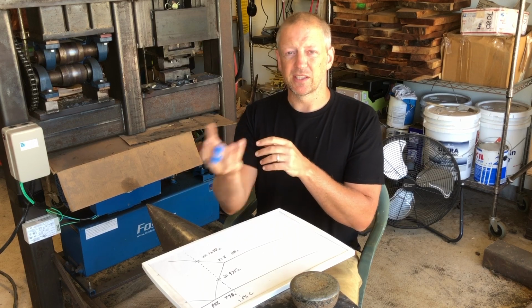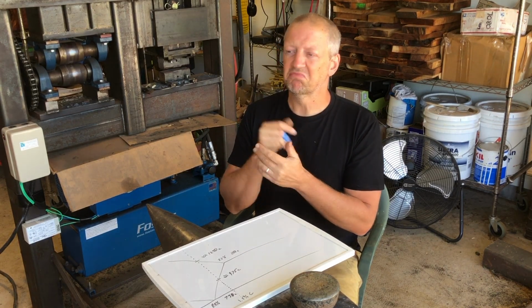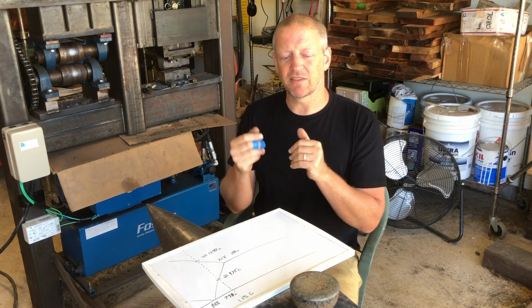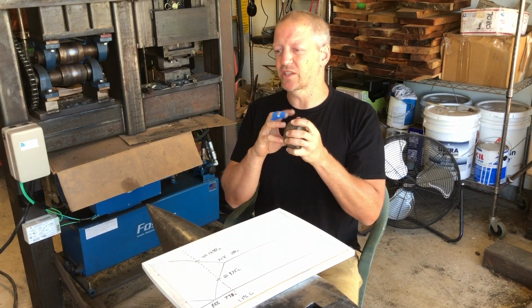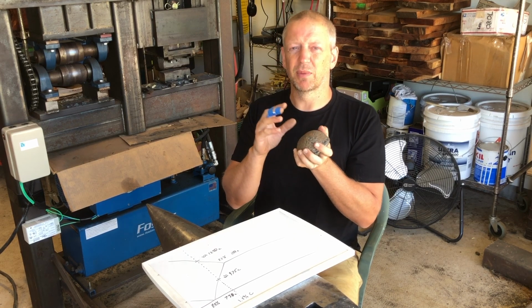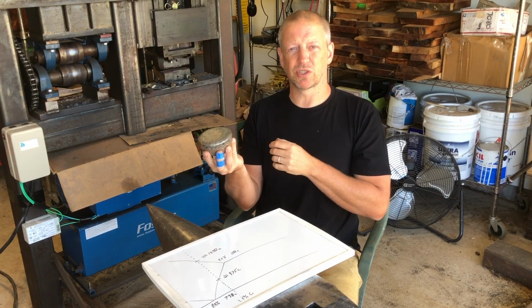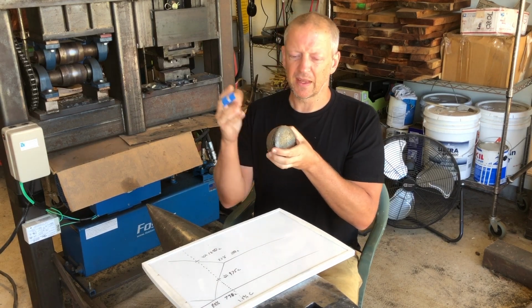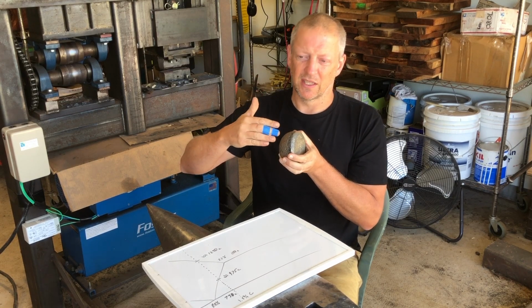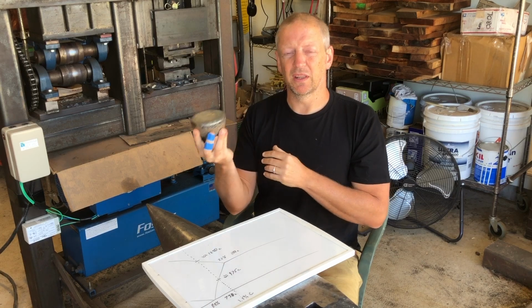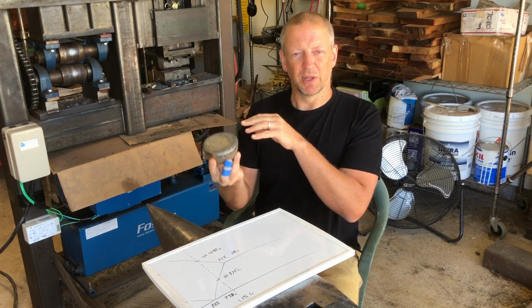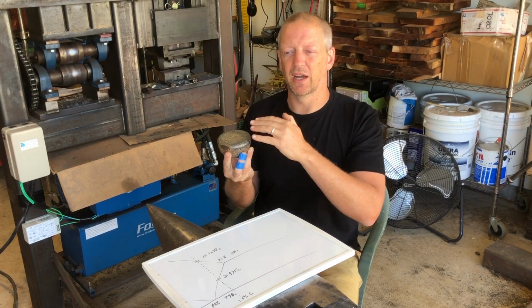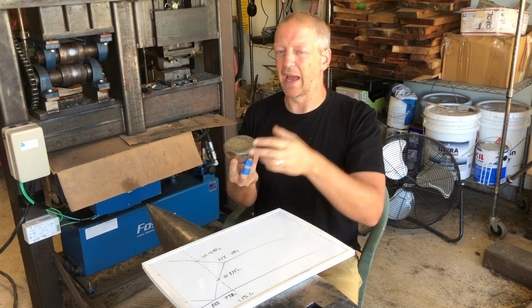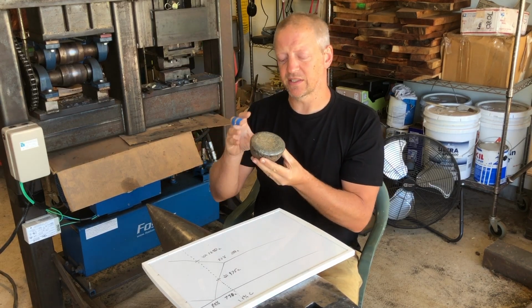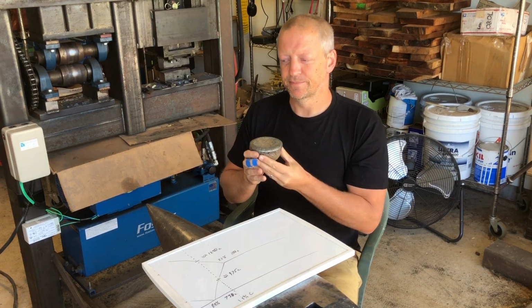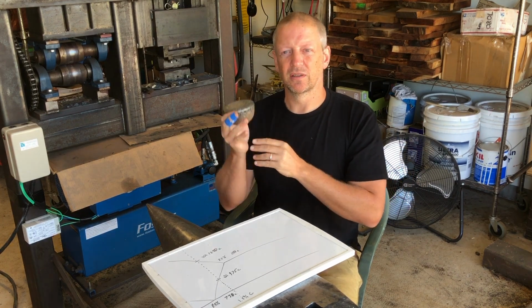So having a process in which you roast the ingot for a while and then test it, do I feel like it's going to forge now? That gives you the opportunity to, in essence, adjust not just the structure of the ingot, but also to some degree the chemistry of the ingot, because that whole time that it is roasting, it is losing carbon. And if we assume that carbon contents in the ingots varied, it could be that you were going to occasionally get a much higher carbon ingot, but through that roasting process, you're going to at least bring that carbon content down somewhat. And especially if you allow the roasting process to continue as long as necessary to create that forgeable ingot, you're going to even out some of that variation with this follow-up process.